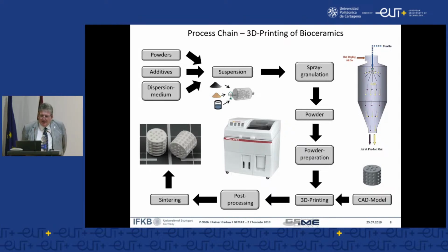And with this material, we go in an apparatus shown right-hand side, that is a so-called spray dryer, a big apparatus, in this case working under the conditions of the pharmaceutical industries, that means with high cleanliness and so on. And we take the suspension and we use a special type of nozzle, and we build a spray. And there is a counterflow of hot air, so that the little droplets form more or less perfect little balls, and the balls will dry, and following the gravity we have on Earth, the product is collected at the bottom. That means the intermediate product, which is used for all the printing processes, is a special blend of bioceramic powder.